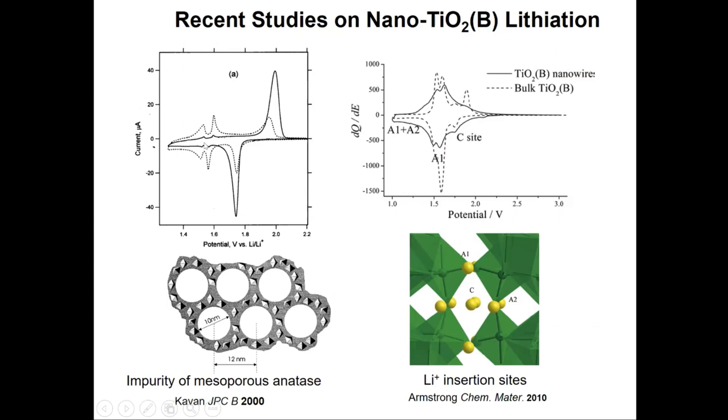it for anatase. And depending on the processing conditions, they argued that what was happening is that they were forming amorphous TiO2 within this little crystalline, nanocrystalline anatase matrix that was templated by the use of a block copolymer, right?